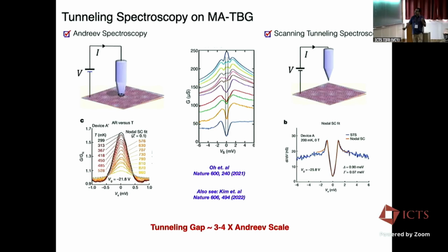The fact that you almost see a gap is because this part is dominated by electrons trying to tunnel, and you don't get enough states if you are in the gap, within the gap at low bias. Here, the standard lore would be that what you are seeing is Cooper pairs tunneling, which can tunnel at zero density of states and so on. And that's what is giving rise to the excess conductance here.